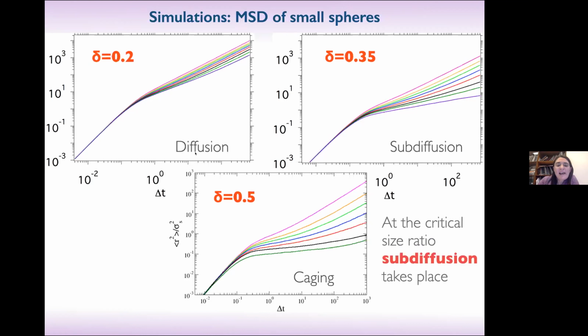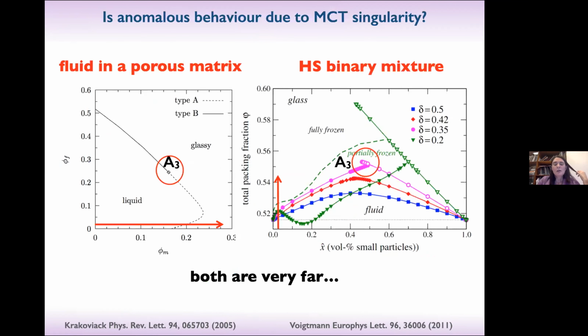For small delta, the small particles are just diffusive because they are not localized. For intermediate delta, you start to see this huge range of subdiffusion that accompanies the logarithmic behavior of the density correlator. And then you increase delta more and you have caging. So let's now try to understand if this is related to an MCT singularity.